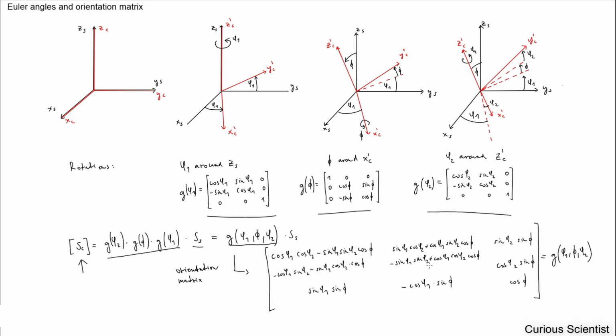The three consecutive rotations can be described by three 3x3 matrices, and at the end you can apply this at once by a huge matrix, which is still 3x3 but has a lot of long formulas in it. It's very simple because you just put in the correct numbers. One mistake you can make is you have to decide whether you are using degrees or radians. You have to make it clear at the beginning of the process, because otherwise you will mess up everything.